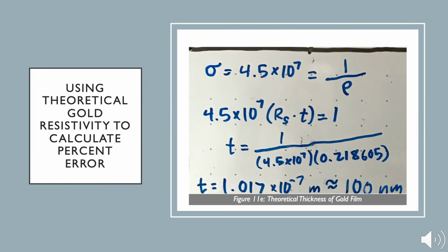Lastly, in Figure 11e, we knew that the product of conductivity, sheet resistance, and the thickness of the sheet is equal to 1. With the known conductivity of gold, which is the inverse of resistivity, we calculated sheet resistance to determine the thickness of the film. We determined the experimental value was 101.7 nanometers thick. With a theoretical value of 100 nanometers, the calculated percent error was 1.7%. The results proved that with this incredibly small percent error, the machine was in fact functioning properly.